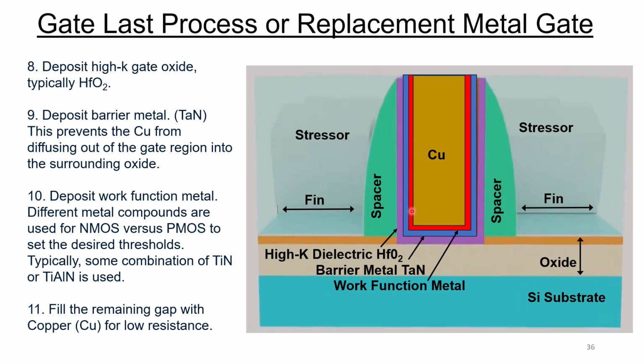Step number 10 is we deposit the work function metal. That's shown in red here. And different metal compounds are used for the NMOS versus the PMOS to set the desired thresholds. Typically, it's going to be some combination of titanium nitride or maybe titanium aluminum nitride.